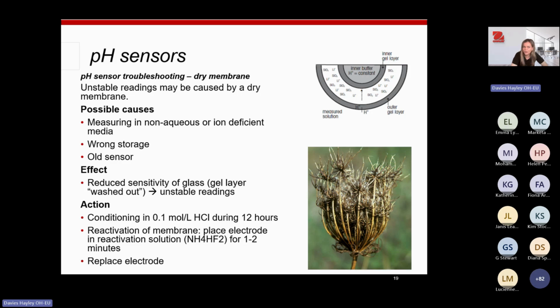You can get a dry membrane if you're measuring in non-aqueous or ion-deficient media or solutions. If you've put it in the wrong storage, for instance if you've stored it in water, or if it's just an old sensor. An old dry membrane will result in reduced sensitivity of the glass, and the gel layer inside is just washed out. It gives unstable readings, so we can try and condition it. You can condition this in a 0.1 molar HCl solution for 12 hours. So you can pop that in overnight, leave it in that solution to really try to hydrate and reactivate the membrane.